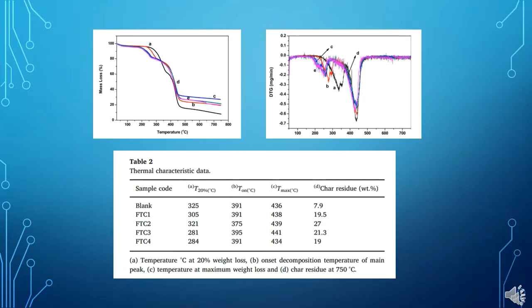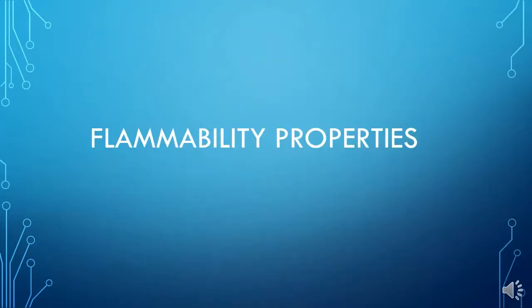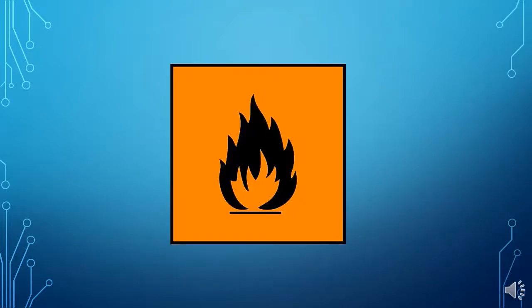It is important to note that the improvement in thermal stability of treated textile fabrics clarified mainly from the enhancement in onset decomposition temperature of the main step in addition to the enhancement in the maximum temperature. The next one will be the flammability properties. The flammability properties of untreated and treated textile fabrics were evaluated based on rate of burning, which reflects the flame retardation in textile samples according to the modified ISO standard 3795.